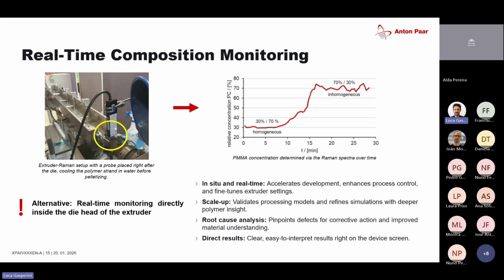But up here at 70% PC, we were not able to get a clear signal. This could be due to two reasons. Either the extruder was not working the way it should, so the sample was very heterogeneous. But for PC and PMMA, what is also interesting is that on a physical level these two mix very well with each other, but on a chemical level they don't. So you can also use this to get an idea of how your formulation behaves during compounding. You could do this with copolymers or mixtures of different polymers, or you can also use this for additives, for example.